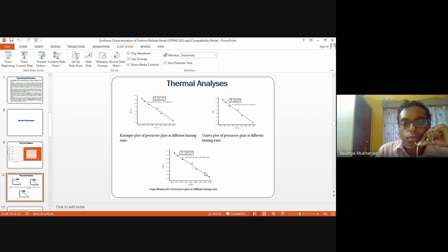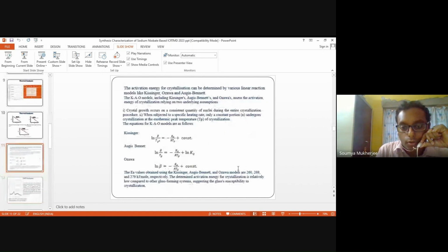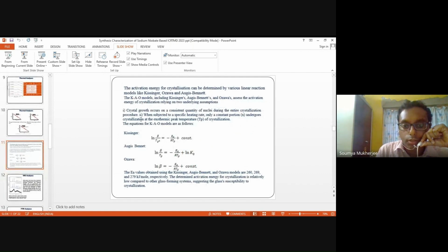Moreover, we have also analyzed the activation energy for crystallization developing from the glassy matrix, leading to glass ceramics, and it has been carried out with the help of the Kissinger plot, Ozawa plot, and Augis-Bennett plot. Following are the equations that have been utilized for Kissinger, Augis-Bennett, and Ozawa, and the values for activation energies are 260 kilojoule per mole from Kissinger. For Augis-Bennett, it is 269, and from Ozawa, it is 279.